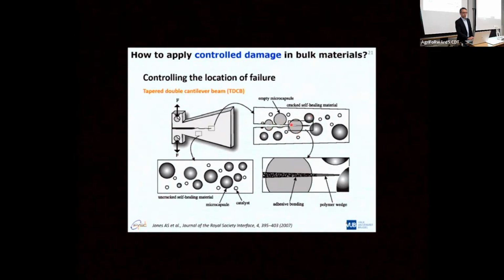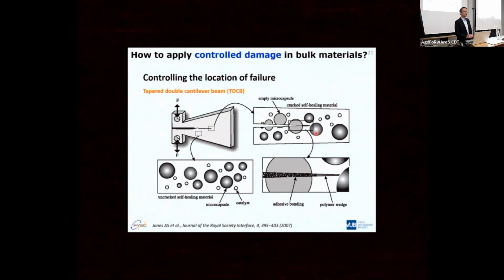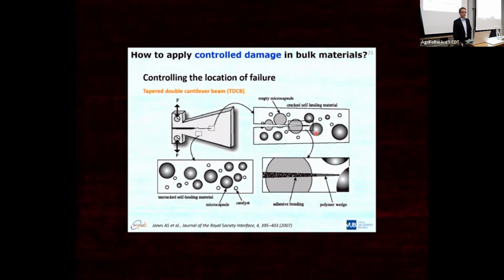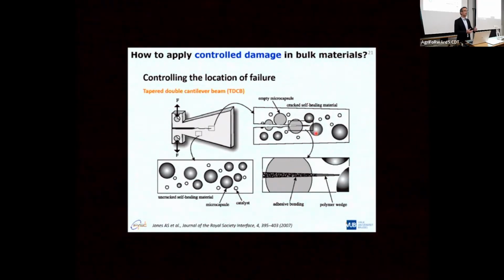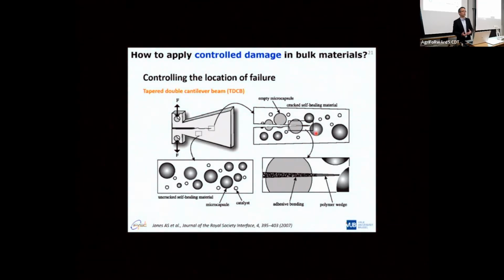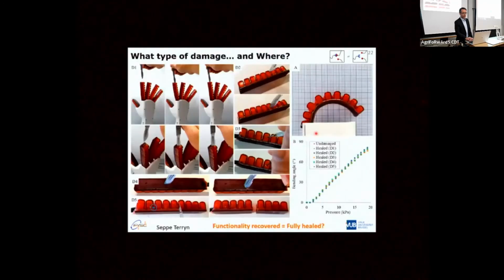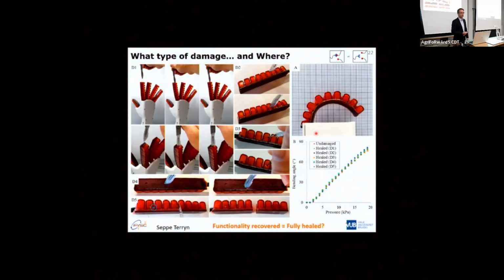They not only worked with, for example, capsules that were there with healing agent coming out of it, but they even did things like just putting the healing agent into the crack plane, letting it heal for some time as a first test to see whether that kind of healing agent might work or not. So there are certainly different ways to approach this, but okay, for the, let's say, the more glassy materials, this was a very nice test to do. And I will show some curves recorded with it a bit later.